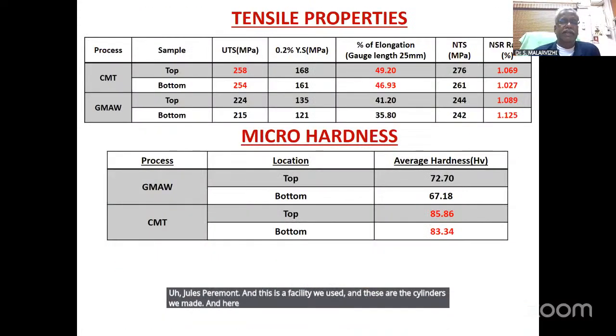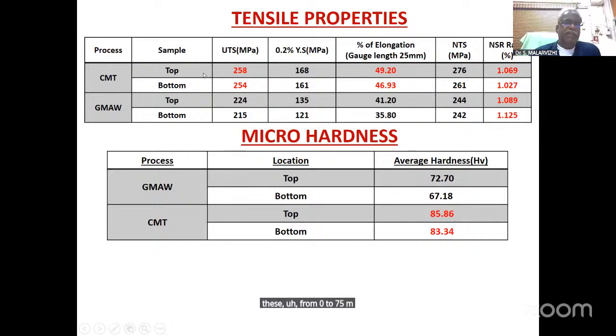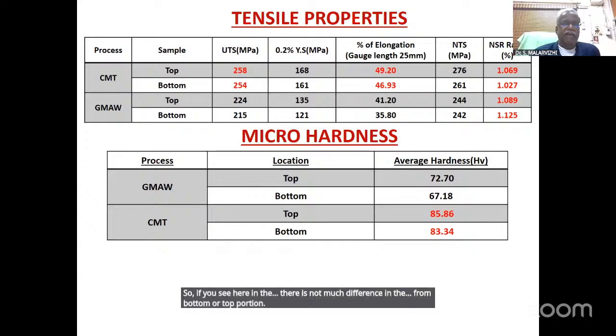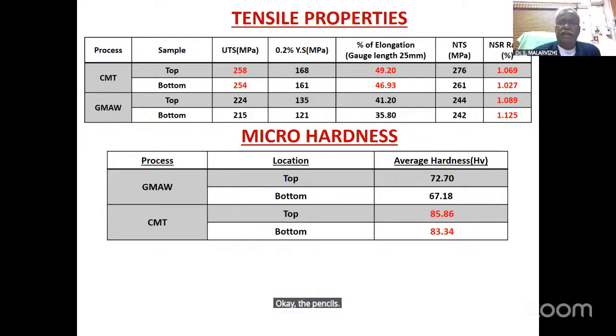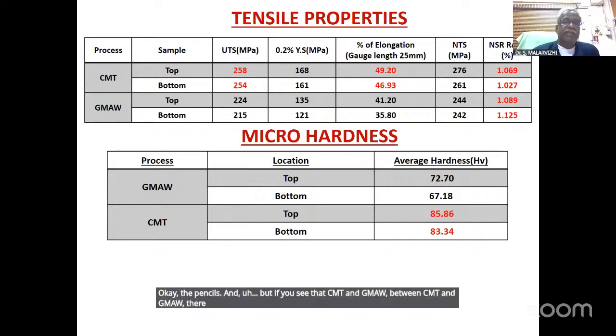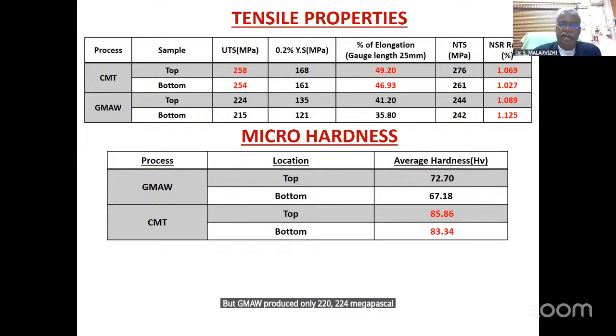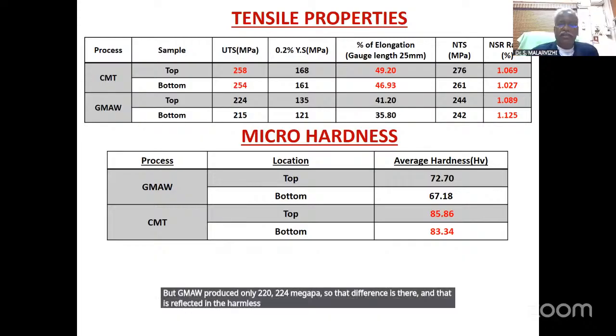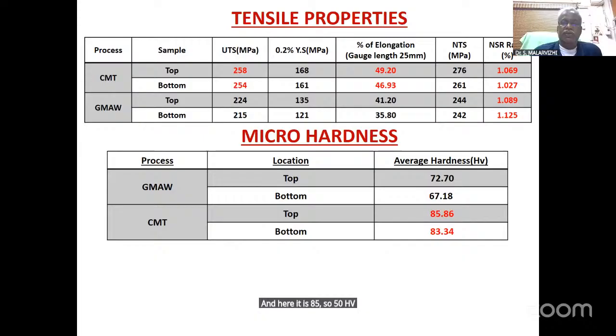Here we made two portions. One is the bottom portion, from 0 to 75 mm. From 75 mm to 150 mm, we made the top portion. There is not much difference in the tensile strength between the bottom and top portions. But between CMT and GMAW, there is an appreciable variation in the tensile strength. CMT produced nearly 250 megapascal, but GMAW produced only 224 megapascal. That difference is reflected in the hardness values also. In GMAW it is 70 average, and here it is 85. So a 15 HV higher hardness is achieved in the CMT process.